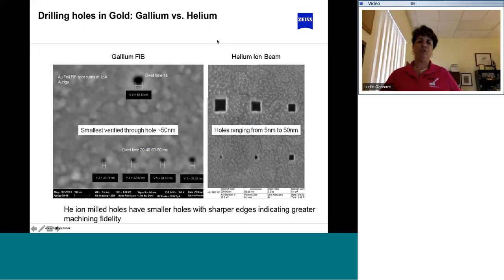And if you're just talking about drilling holes, it's really good for drilling holes in freestanding membranes where you don't get the buildup of helium deep within your sample. So if you have freestanding membranes, you can make extremely small holes. And this is just a comparison between a gallium FIB and a helium ion microscope, and you can see the extremely small holes that are available, down to about 5 nanometers, whereas using a gallium FIB on the same material, you're limited to about 50 nanometers.